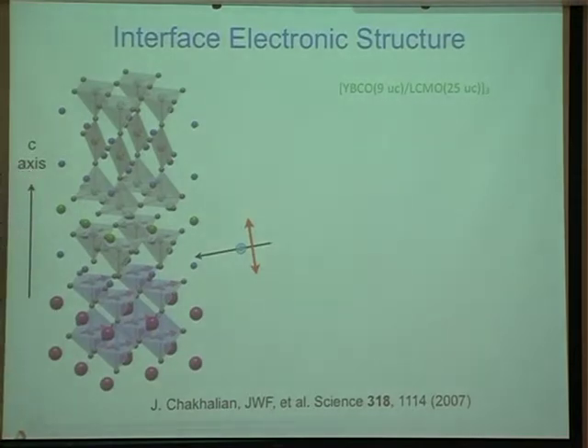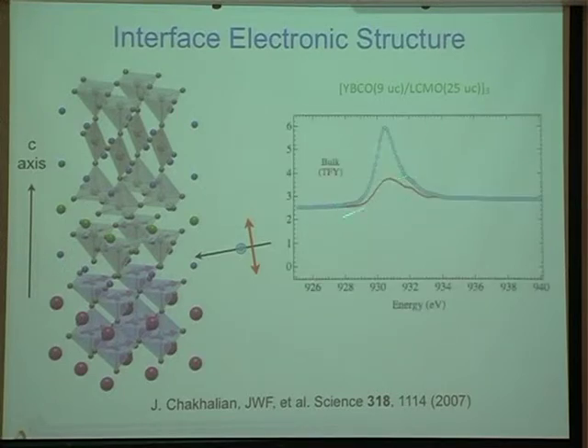When we originally did this, Jack and myself, along with Keimer's group, worked on this back in 2007. We were looking at very thick structures: a very thick layer of superconductor and a very thick layer of ferromagnet, which we stuck together. We had some creative ways to try to tease out the electronic properties at the interface. What we found was that if you measure the bulk of the cuprate, and I come in at a geometry like this, with polarization either out of plane or in plane, you have an extremely large orbital polarization.